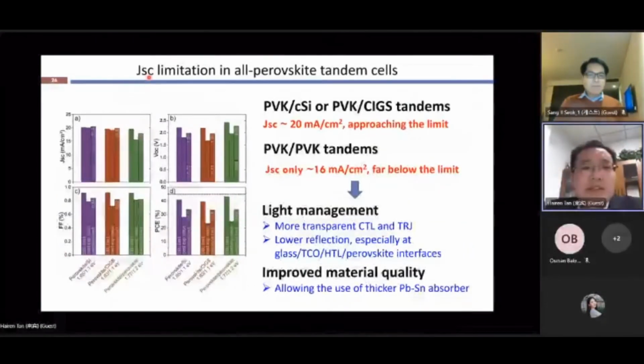Because we know that JSC is a major limitation in these all-perovskite tandem devices compared to crystalline silicon or CIGS tandem devices, which can already get a JSC approaching 20 milliamps per square centimeter, while we can only get 16. I think we have to do more work on light management, especially using more transparent charge transport layers and front electrodes. We also have to manage the surface reflection, which I think is also something neglected in this field. And we have to further improve the materials quality, especially of the mixed lead-tin narrow band gap perovskite, so that we can use an even thicker absorber layer to get higher photocurrent density.